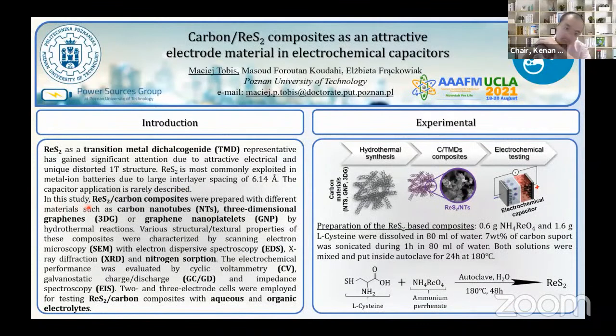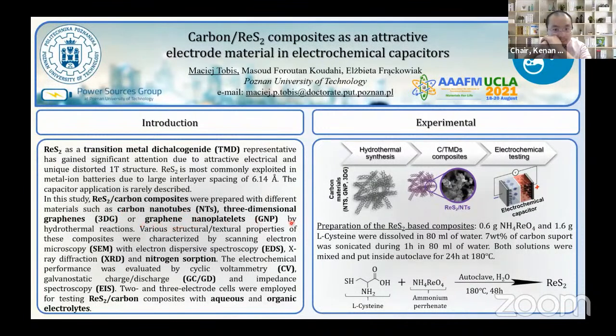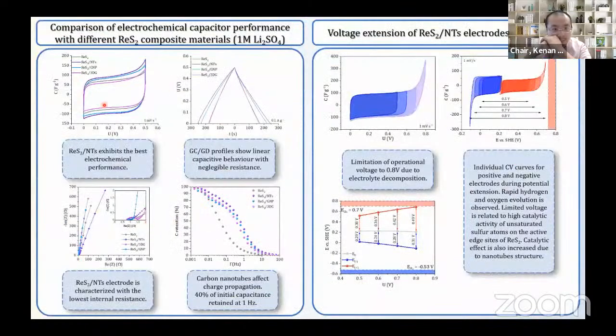To this end, we have prepared various ReS2 carbon composites, for example with carbon nanotubes, three-dimensional graphenes, or graphene nanoplatelets, by hydrothermal reaction, and used them as electrodes in electrochemical capacitors. Here you can see the comparison of electrochemical performances for each of these materials, and it occurs that the best performance was recorded for the rhenium disulfide deposited on the nanotubes. Here specifically you can see that not only the capacitance was improved, but also the charge propagation properties.